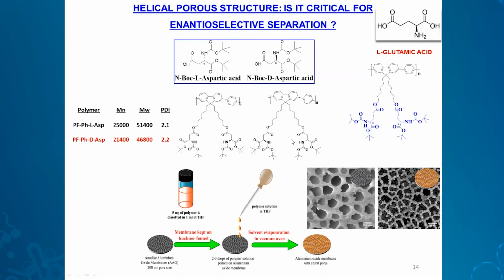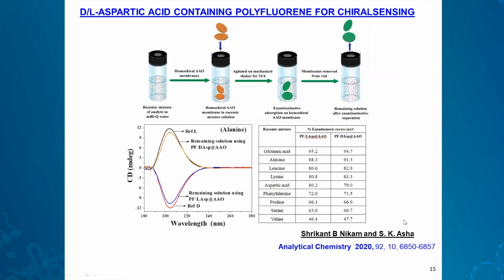Then we thought of the membrane approach. That is, this is a commercially available anodic alumina membrane. So we deposited our polymer on this anodic alumina membrane, as shown here schematically. And this is an SEM image confirming the deposition of the polymer on the membrane. And then we could make different membranes, either the D membrane or the L membrane. Now if you put the membranes into the enantiomeric mixture, the membranes could selectively take up one enantiomer. So supposing you took the D membrane, and this is the L reference compound, the remaining solution is shown here. The D membrane will selectively take up the D isomer, so the solution will be rich in the L isomer.